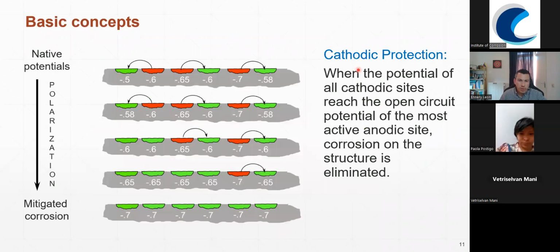So what we want to do with cathodic protection is to avoid those differences in these micro cells that we have within the steel structure. If we avoid the difference between the parts, the micro anodic and micro cathodic parts in the steel structure, we are not going to have corrosion, because basically there is not going to be any driving force for the chemical reactions to take place. So that's why we want to polarize the structure.